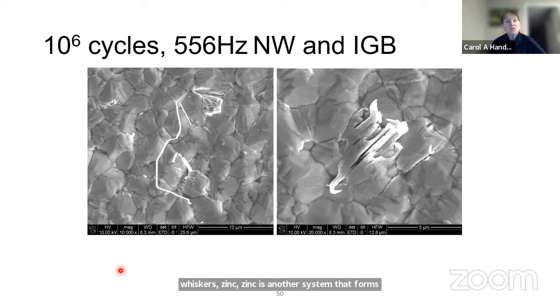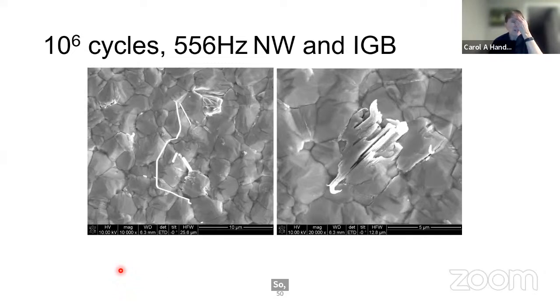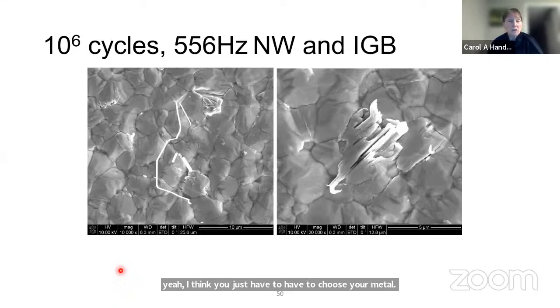And so in server systems, server farms, and this used to be for big computer mainframe systems where you had to have big cooling systems attached, they would have raised floors, and they had to make sure that they didn't use particular zinc films, because they would form whiskers, and then all the whiskers would break off and get sucked into the airflow and cause the computers to fail. So, yeah, I think you just have to choose your metal and decide what temperature regime, and strain regime, you have to go into to force this to happen.